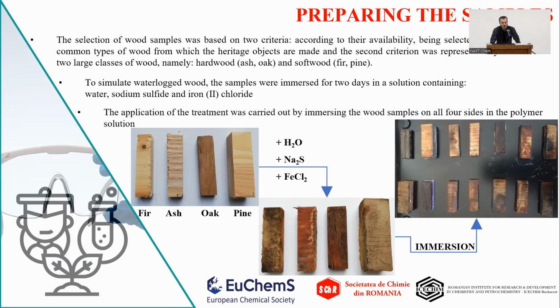To simulate waterlogged wood, the samples were immersed for 2 days in a solution containing water, sodium sulfide, and iron chloride 2. You can see the result in the picture in the middle. And the application of the treatment was carried out by immersing the wood samples on all 4 sides in the polymer solution. You can see that in the picture on the right of the slide.